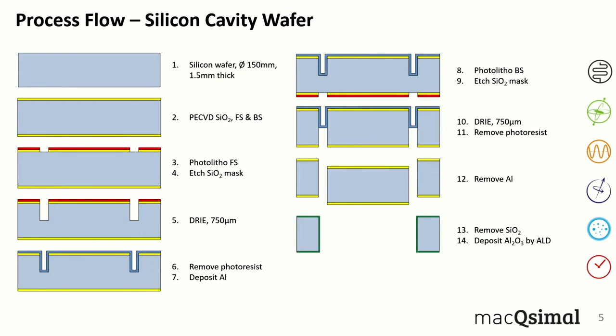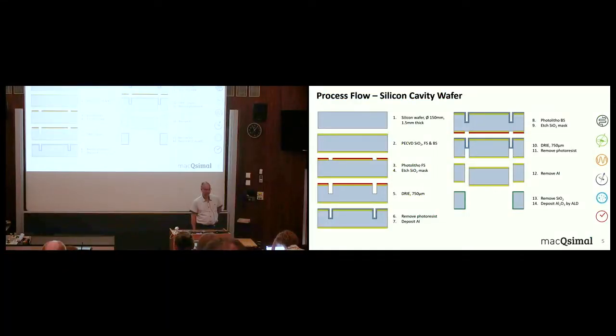So now coming in detail to the process flow, as already mentioned, we start with a silicon wafer of 150 millimeter diameter, 1.5 millimeter thick. Then we deposit oxide on both sides of the wafer. We make a first photolithography on the front side and pattern the oxide. And we use this double mask of photoresist and oxide to etch very deep trenches by deep reactive ion etching. We go up to about half of the depth of the wafer, to 750 micrometer.